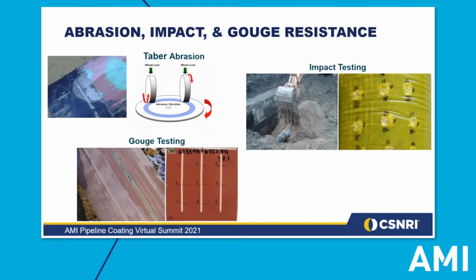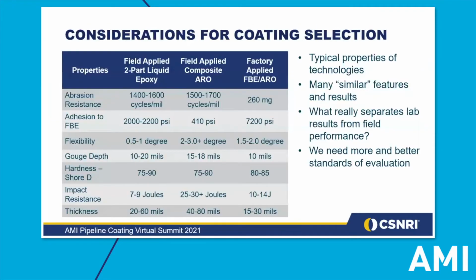Any shear scratching to the coating has the potential to develop a crack that may travel and over time expose the steel to corrosive environments. Abrasion, impact, and gouge are prevalent forms of coating damage that should be considered when reviewing material properties.